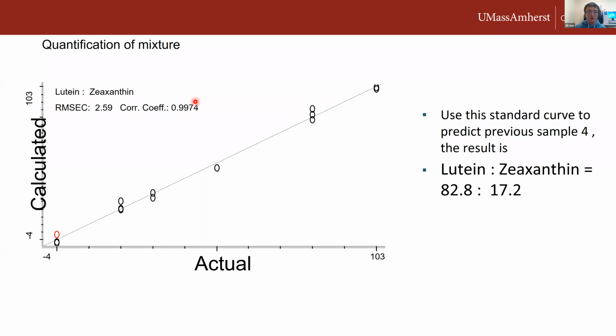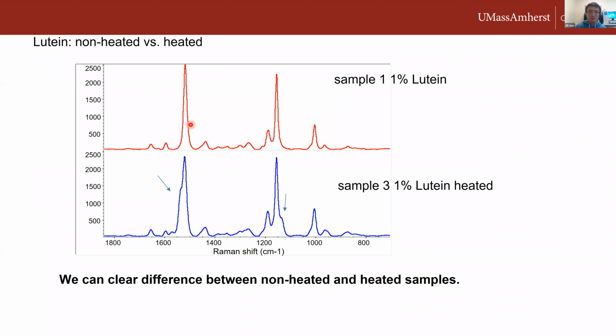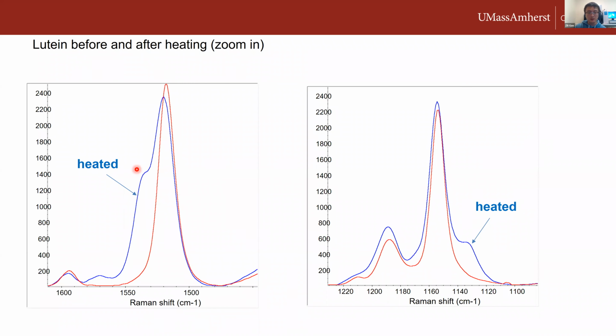As you can see, we have a coefficient of 0.9974, and this is a very powerful method that we can use to identify different structures even in the isoform. Besides that, we also found that after the heat treatment, lutein showed a slight shift or a new peak at this position. And when we enlarge this peak, we found that this is a significant change. And in this way, we are able to identify the stability of your compound after different treatment.